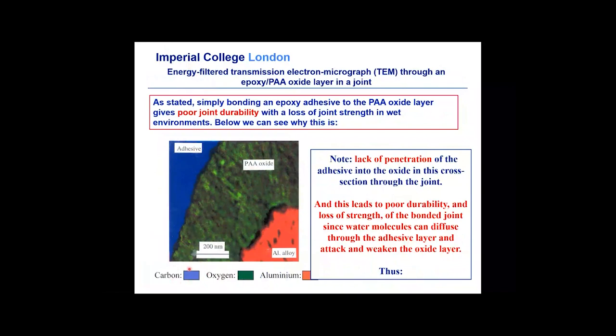Now the blue is carbon, the green is the oxygen, obviously from the aluminium oxide, and this is the aluminium alloy underlying the oxide. But the important thing to see is there is no blue penetrating into the oxide. So there's no adhesive at all penetrating into the oxide structure. The adhesive is simply sitting on top of the oxide. And remember, this is like open drinking straws. And therefore, what you get is a very weak interface, and water comes in, goes into the empty drinking straws, which is the oxide, attacks and weakens the interface and the oxide, and you get premature failure.